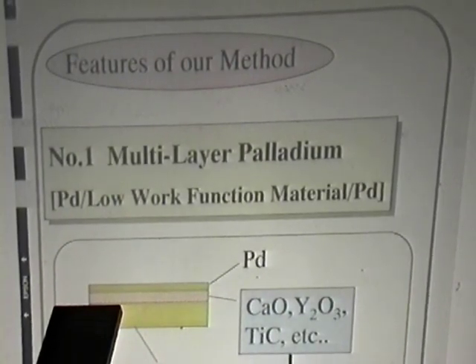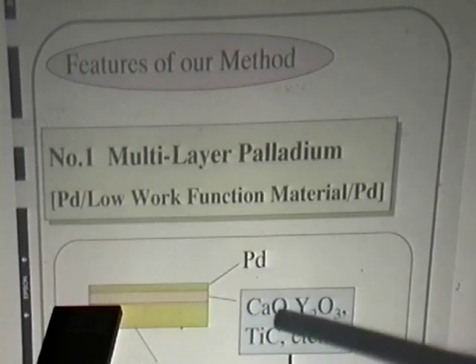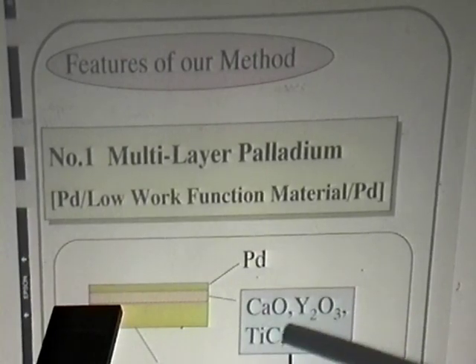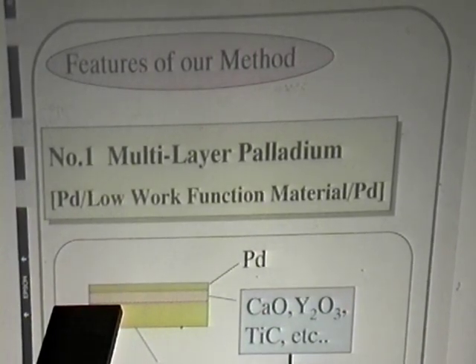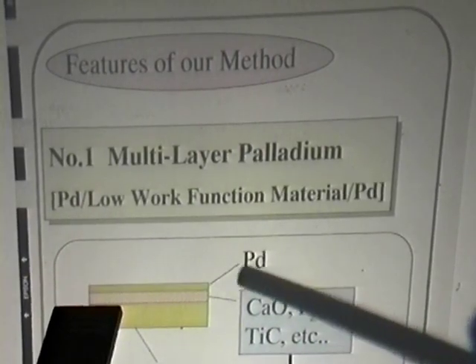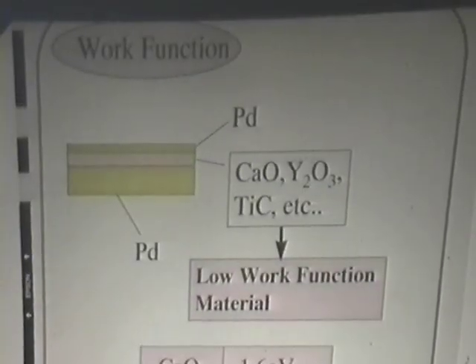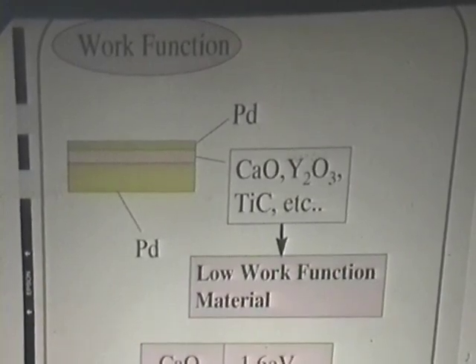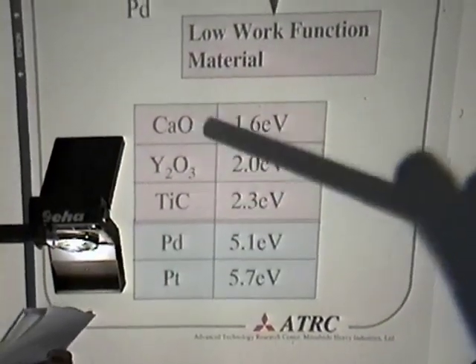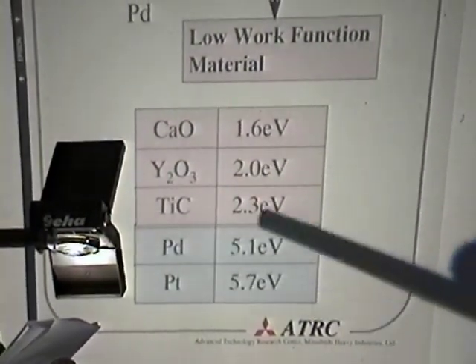This transparency shows the first feature of our method. We developed multilayer palladium which contains low work function material. It is composed of palladium seed and calcium oxide or Y2O3 or TiC, which are low work function materials, and palladium thin film. You can see by this transparency that the work function of CaO, Y2O3 and TiC is lower than palladium.